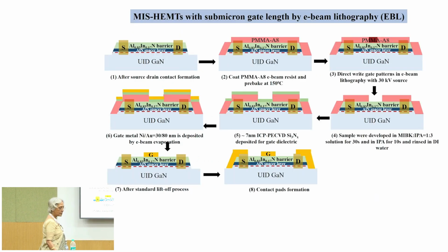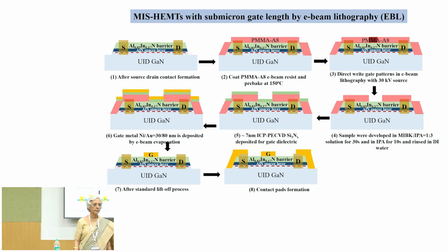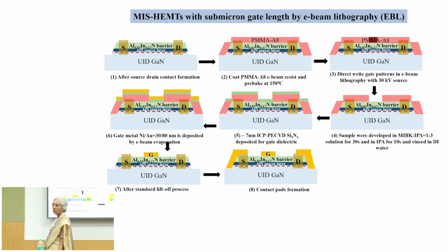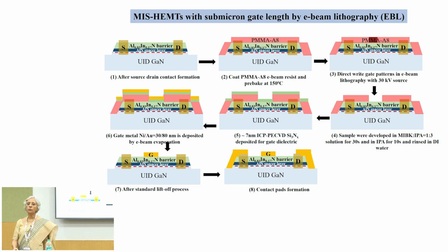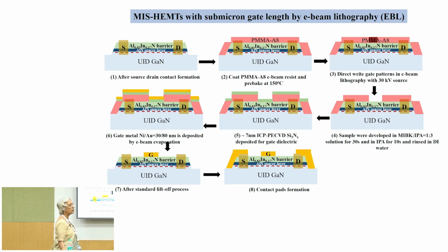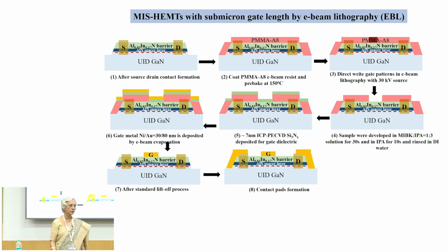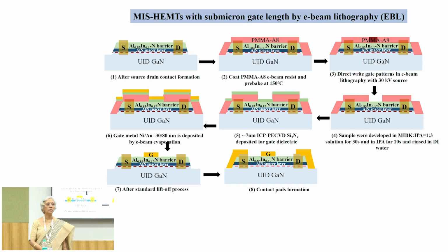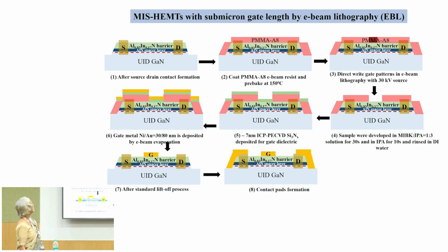So, obviously then if we are going to work on aluminum indium nitride gallium nitride heterojunction, then we need to work on MIS HEMTs, where we will introduce a thin gate dielectric between the gate and the barrier in order to reduce the gate leakage current. And this is the figure, the process steps for submicron gate length MIS HEMTs with e-beam lithography.